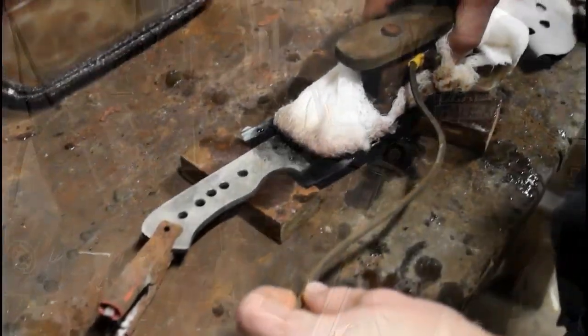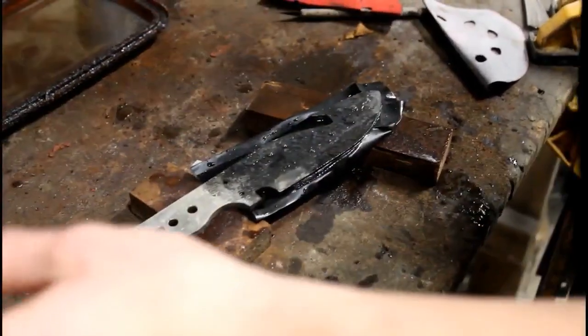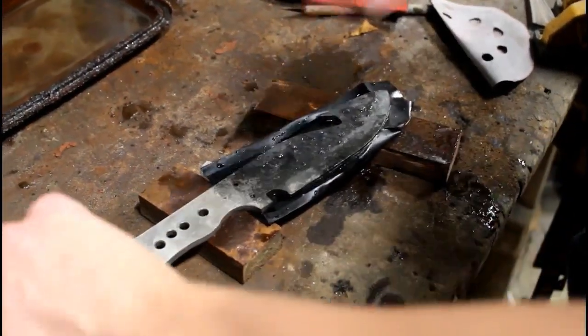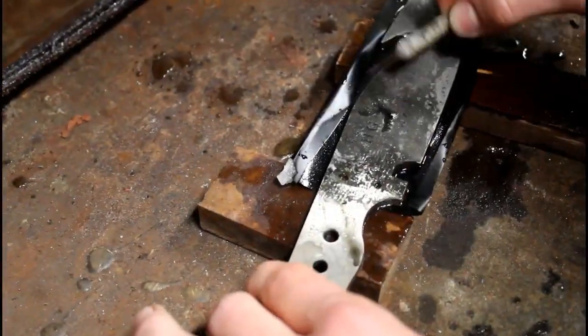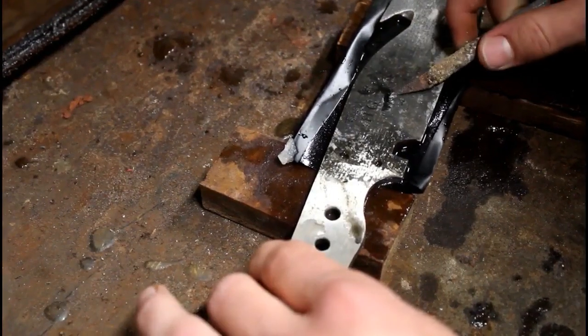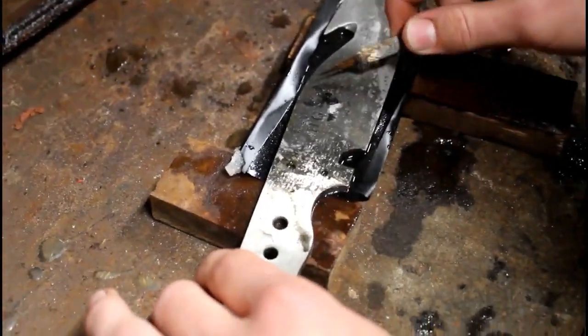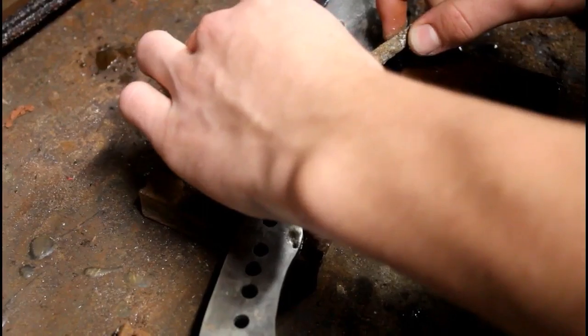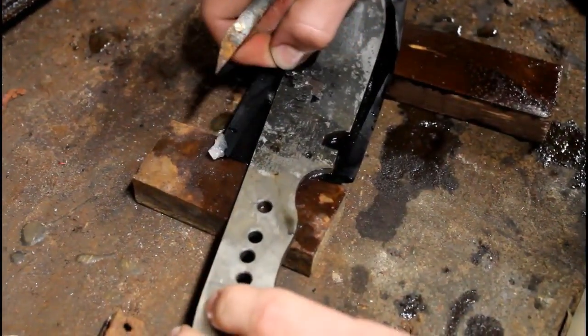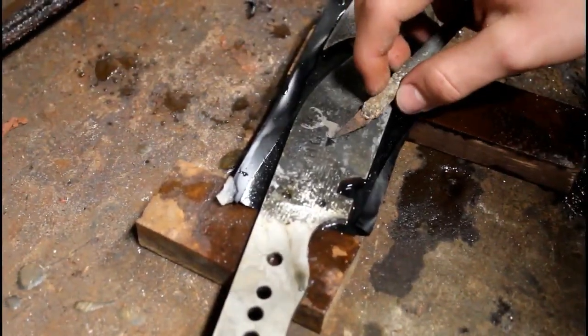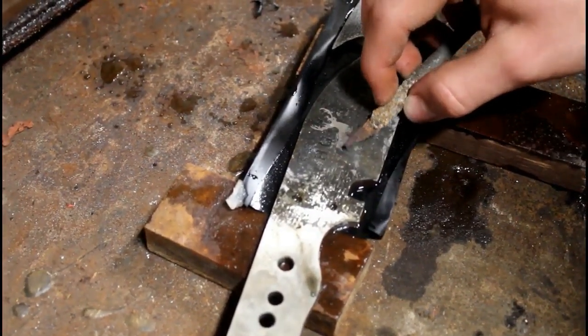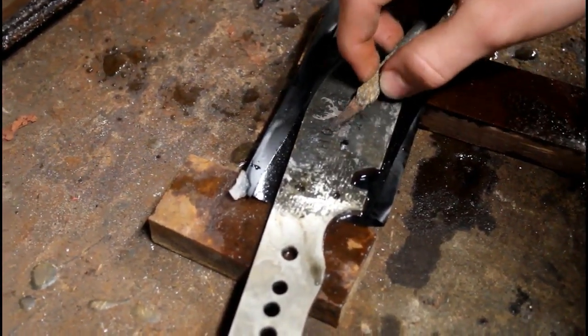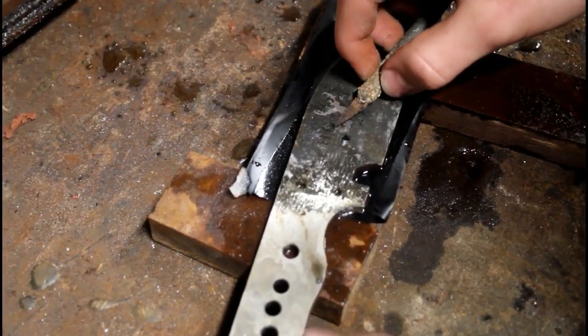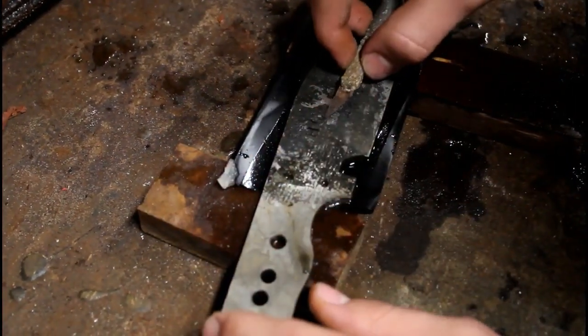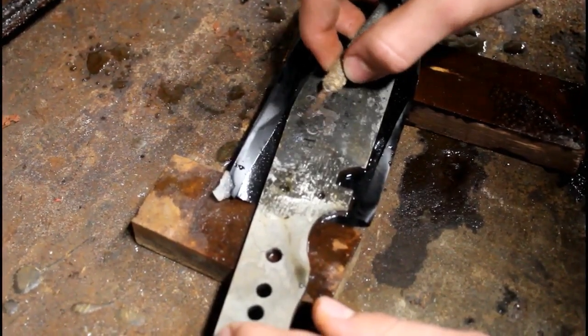Alright, so now we're going to move on to etching. We do electro etching. So this is done with a car battery charger, a solution of white vinegar and salt. We cut out a stencil from self-adhesive vinyl, and that acts as the resist. Basically anything that's covered with that vinyl will remain shiny, and anything that's exposed to the etching will get the etched texture. So after the etching, and this is etched for a total of about 3 minutes at 12 volts, 2 amps, done in 30-second increments with a little bit of cooling time in between.